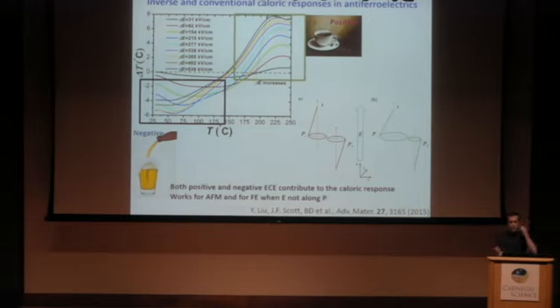And to explain this, basically, the idea is the following. You take a kind of antiferroelectric state, so dipole up, dipole down, and then you apply an electric field along that direction, for instance. What will happen at the beginning? This one wants to turn to follow the electric field. But of course, at the beginning, it was ordered. And then it starts to disorder before reordering. You see? If you start with a system which is ordered, and then you go toward disorder, then you have delta T negative. Okay?